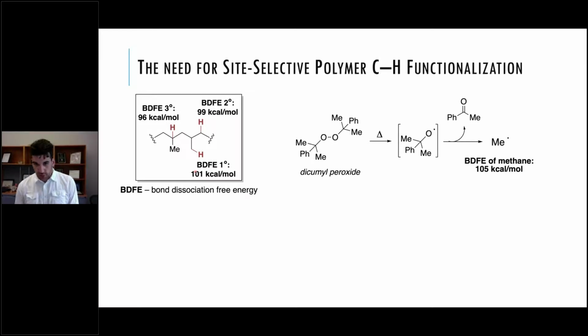Usually, if we want to do a reaction with these materials, we put them in an extruder with a peroxide, and this peroxide will create a radical that can react with one of these CH bonds. But that radical only has a bond free energy difference of anywhere between 9 and 4 kilocalories per mole relative to these. So if you're trying to do a reaction with a material that doesn't have a much higher bond strength than the bonds you're trying to react with, there's not a large thermodynamic driving force for that reaction to happen. So a bunch of reactions you don't want to happen do.